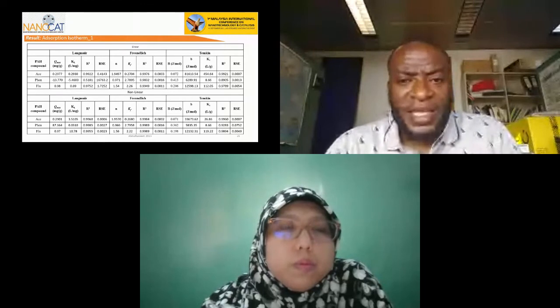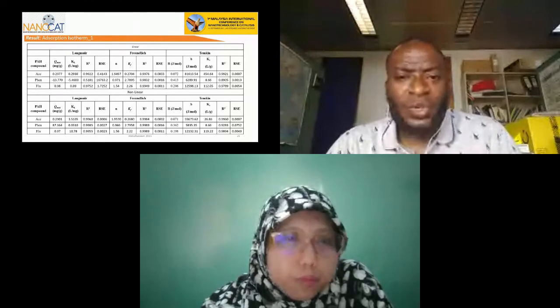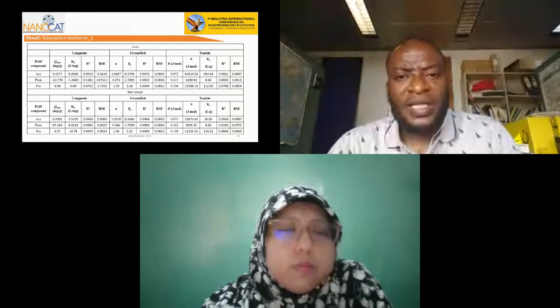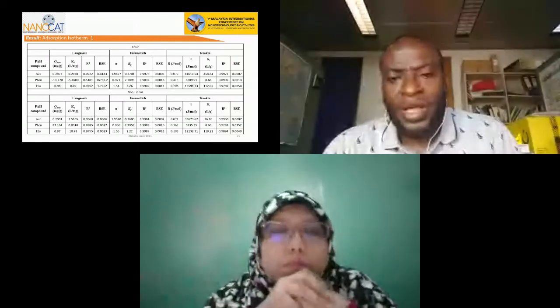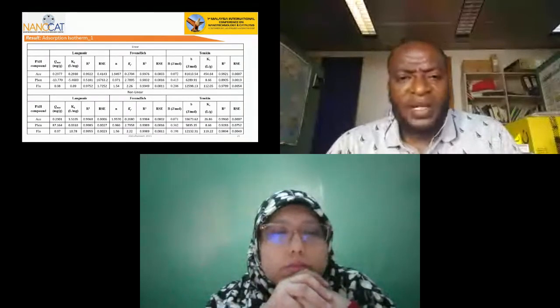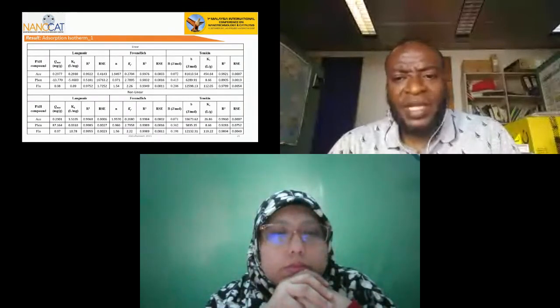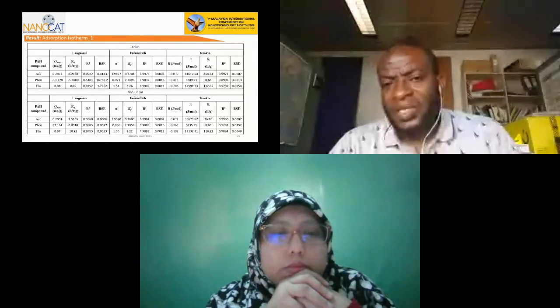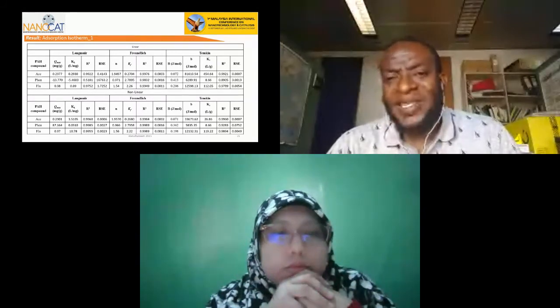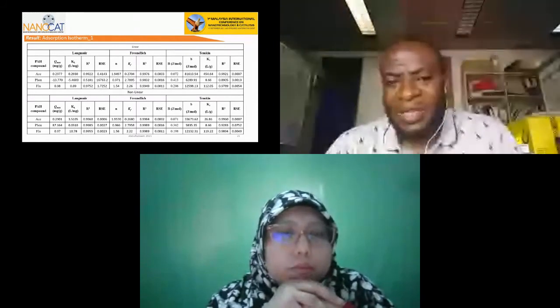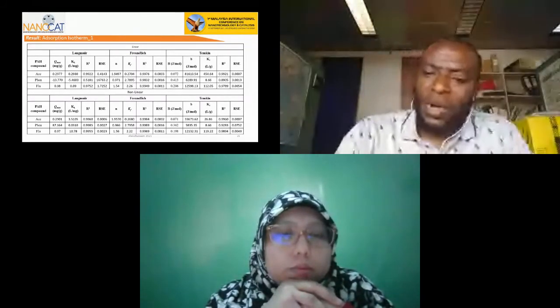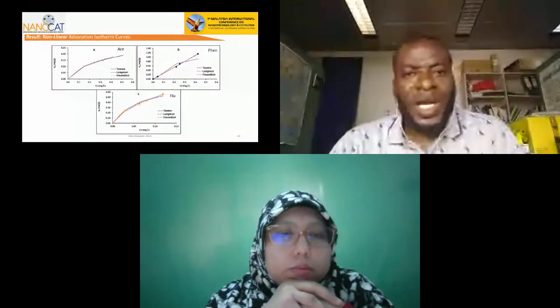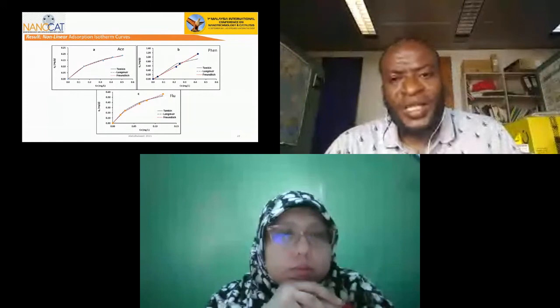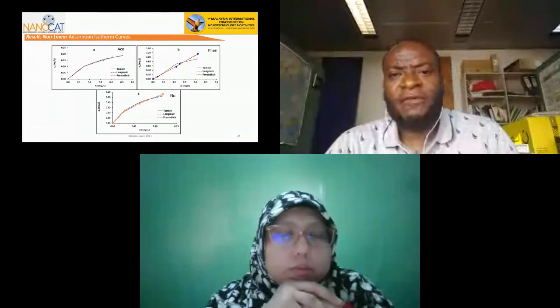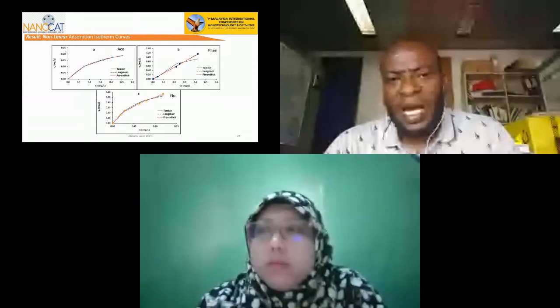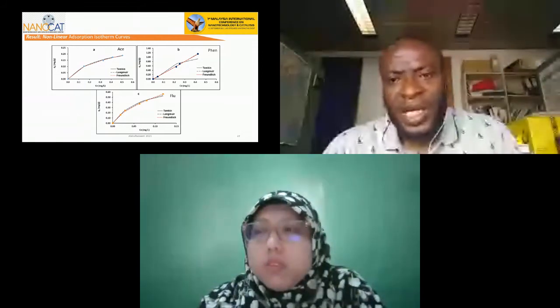And from what we can see here, Freundlich happens to be the best model to describe the isotherm of these PAHs on the adsorbent. And of course, from the nonlinear point of view, Langmuir and Temkin did not do badly either. So this suggests that we can have coexistence of many mechanisms responsible for adsorption of these PAHs on the adsorbent. And from the curve, we do see that the nature of the curve also shows that it is favorable for adsorption to take place between these PAHs and the adsorbent.